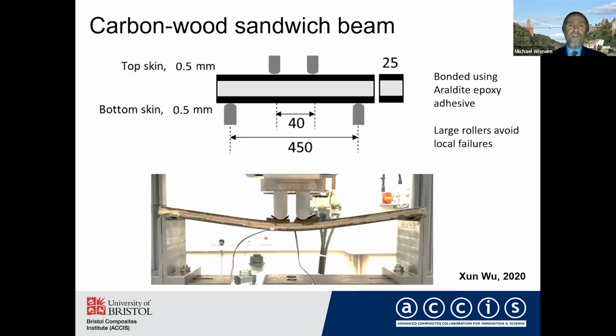More recently, Xun Wu has developed this carbon wood sandwich beam, which is a very nice test method, and I think we're going to use this quite a lot in the future. In this case you've got carbon fiber skins, top and bottom, bonded to a wood core. Wood is very good because it has a high shear strength and supports the carbon very well, so you don't get failures locally influenced by, for example, the use of honeycomb core. There are issues to do with localized stresses at the core. So this seems to do a pretty good job. And provided you use large enough rollers, you can avoid local failures and get a good compressive failure with this type of test.